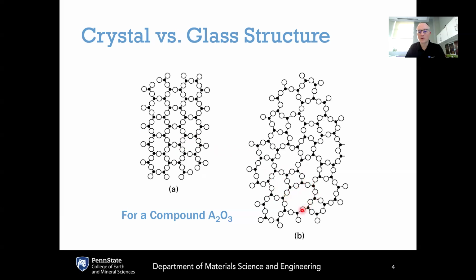Here, there's a larger ring. So this ring has 1, 2, 3, 4, 5, 6, 7, 8 cations in the ring. So this is an 8-membered ring. And as a result, from an intermediate range order perspective, there's a variation in the ring size, and this ring size distribution contributes to the disorder of the glassy state structure. So well-defined basic structural unit of the triangle, but different numbers of triangular units come together to form different sized rings, and being able to fit all these rings together is what then leads to the greater disorder at the intermediate range scale and then at the longer scale.